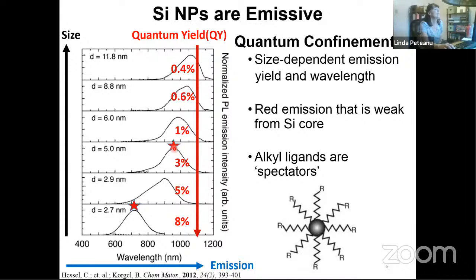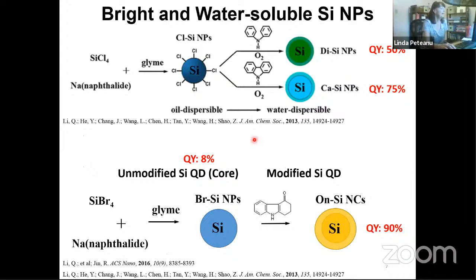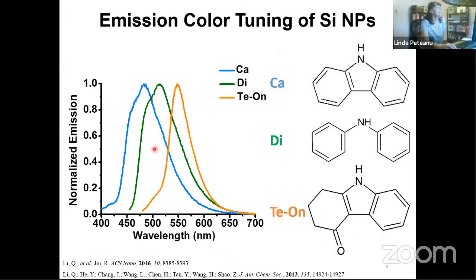So remembering these wavelengths, and also that the core emission is weak and red, what I'd like you to do as we go forward. So a number of groups, including Rong-Chao Jin's group, began to experiment with changing the ligands on the surface from non-emissive or innocent ligands to materials with ring systems. And there it was found that you can go from a quantum yield of 8% up to a quantum yield of about 90%, depending on the properties of the ligands. And moreover, you can tune the color depending on what ligand is chosen. So here you see emission from 3 different ligands that are chosen. You can span the region from blue to orange in this particular case, depending on structural changes.